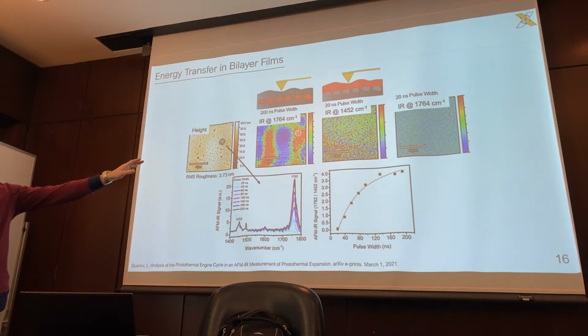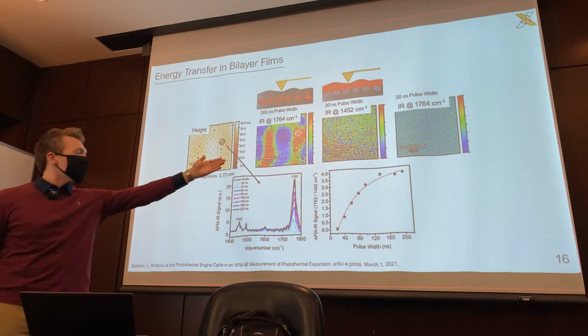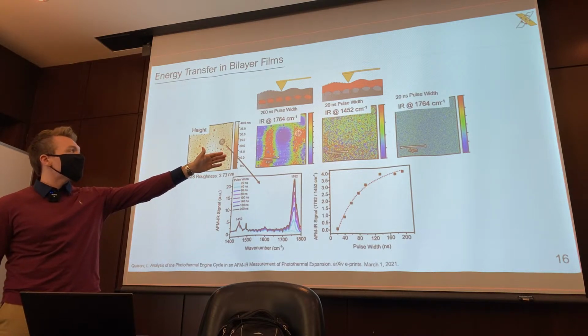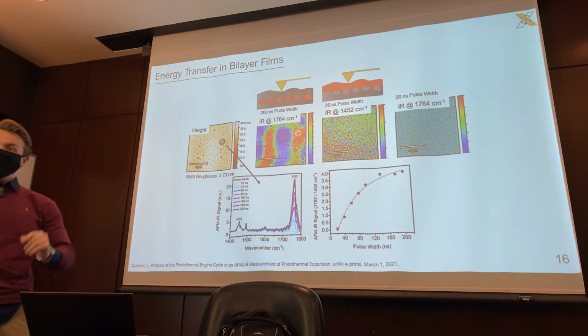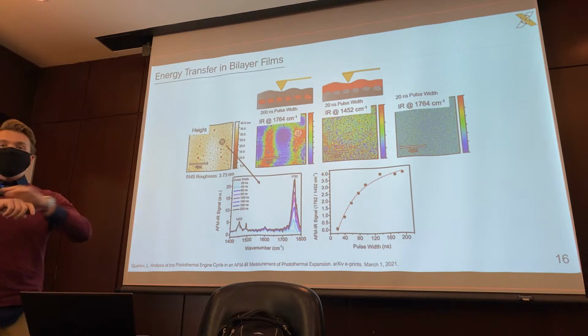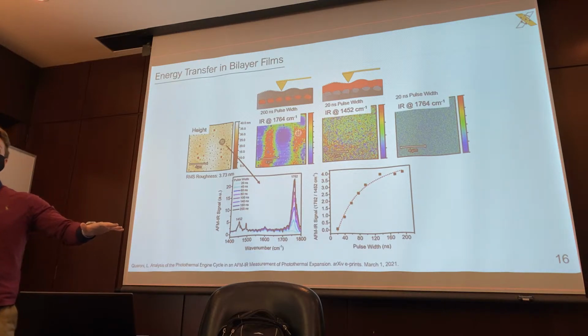And what you're seeing here at 1452 is just the polystyrene. If we measure it again at 1764 on the far right-hand side at 20 nanoseconds, that short pulse width, again, we just see noise. It's nothing.